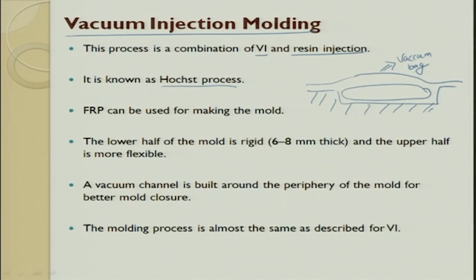Good advantage. Second thing is, whatever was the shape of the component you want to make, which is guided through a die, the vacuum bag takes that profile. So, that helps you in getting the top surface also smooth, a complete finished part. The lower half of the mold is rigid, as I said, and the upper half is flexible. So, it can be made out of rubber, it can be made out of a polymer, it can be a bag, whatever it is. The vacuum channel is built around the periphery of the mold for better mold closure.